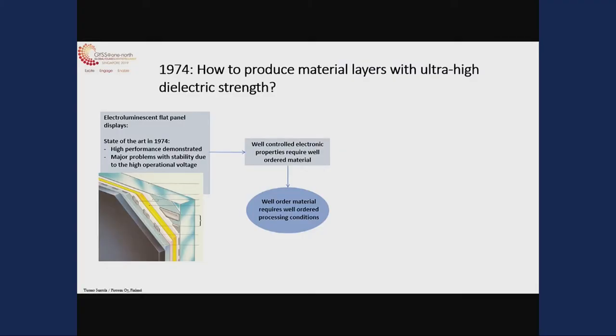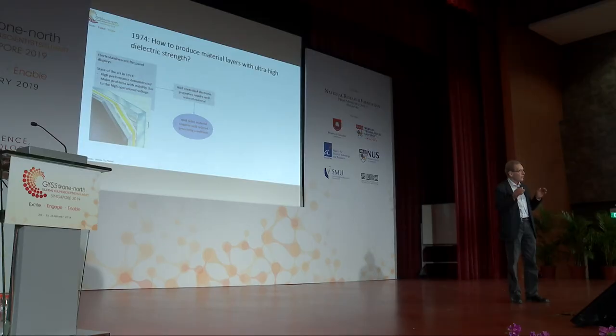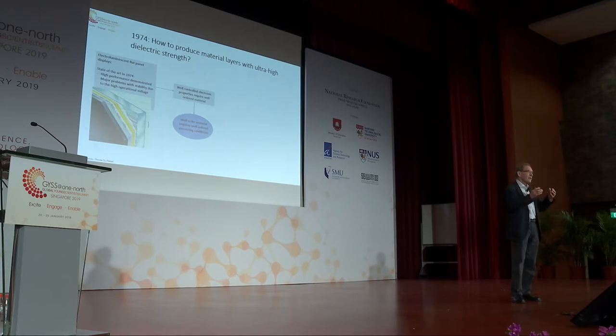Using the traditional thin-film methods, there are certain limitations in controlling the structure. We generally get a kind of nucleation that creates a polycrystalline material with grain boundaries and other types of disorder. So for going beyond that, we need to think about the growth process itself — so that if we first transfer material and then start ordering it, it's very difficult to get to perfection. What could be a way of building order just when making the material?